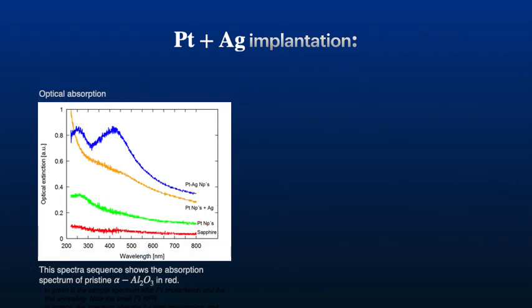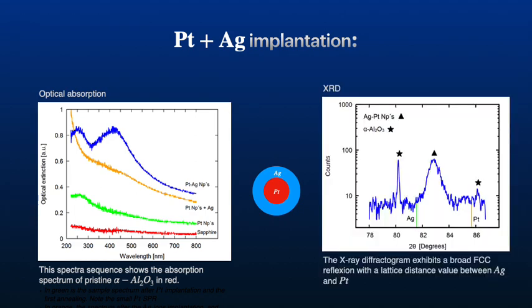The resulting nanoparticles showed a clear local surface plasmon resonance at the wavelength corresponding to pure silver. Compared with simulations by the Mie theory, one finds that this optical response agrees with a core-shell structure with the silver atoms at the shell, which is also thermodynamically favored by its lower surface energy. X-ray diffraction shows that the lattices are very deformed and that a broad region of solid solution must extend across the border. In this example, the reflection corresponding to the 311 plane is located above the silver and below the platinum.